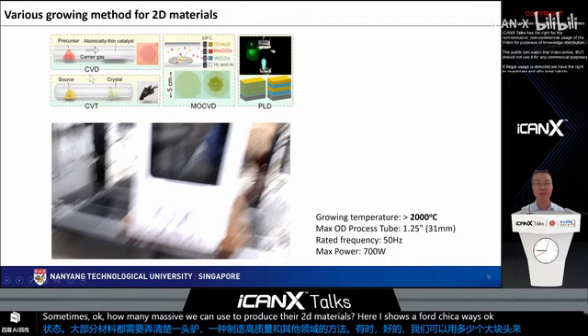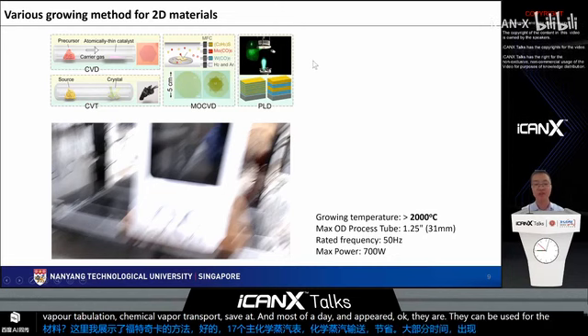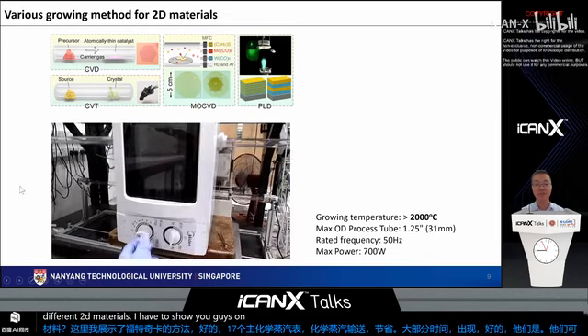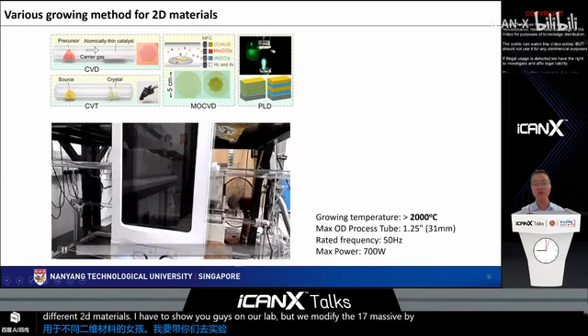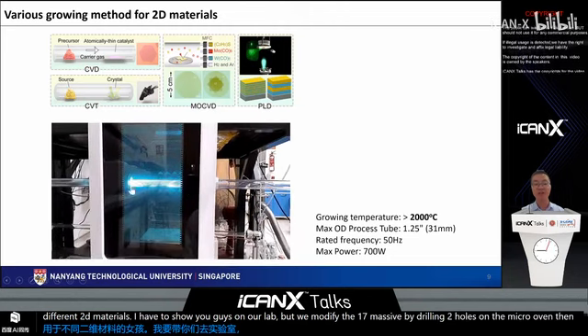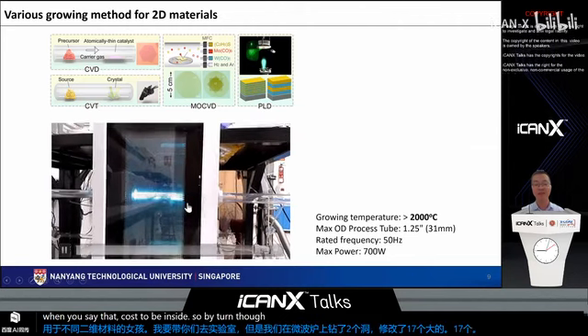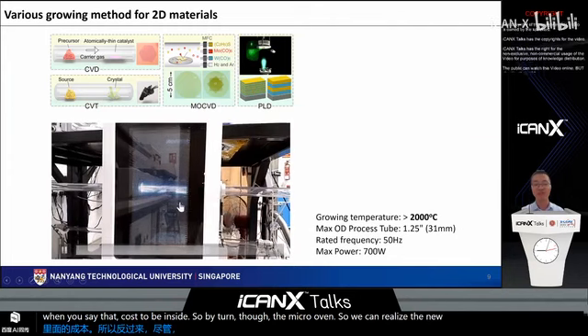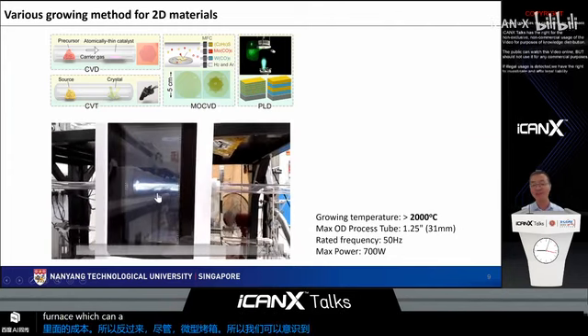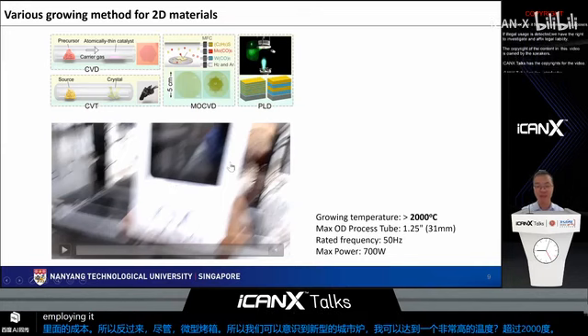So how many methods can we use to produce the 2D materials? Here I show 4 typical ways: CVD, chemical vapor deposition, chemical vapor transport, CVT, MOCVD, and PLD. They can be used for the growth of different 2D materials. Here I just show an example in our lab. We modify the CVD method by drilling 2 holes in the microwave oven. Then we insert the quartz tube inside. By turning on the microwave oven, we can realize a new version of CVD furnace, which can reach a very high temperature, more than 2000 degrees. By doing so, some 2D materials with very high melting point can be realized. So this is how we produce the materials.